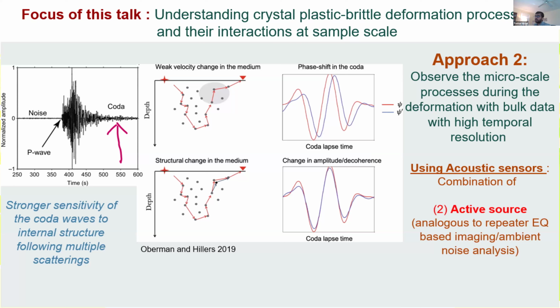This approach is very analogous, or exactly similar, to ambient noise analysis that's done very actively in seismology right now, where we have one source and one receiver. When we send a pulse from the source, it gets scattered in the medium because of defects or damaged sources and so forth, and we receive it at the sensor. If subsequently there's any change in the medium because of deformation processes or fluid flow and so forth, that changes a little bit of the path that the waves are taking. As a consequence, when we look at the waves in the receiver, there are small changes in phase shifts.